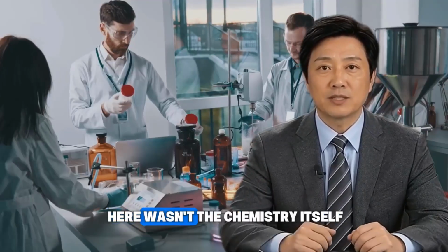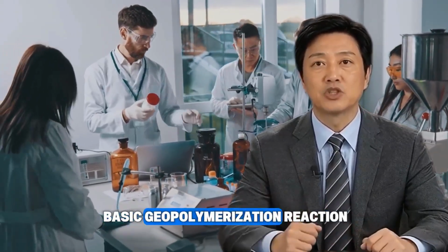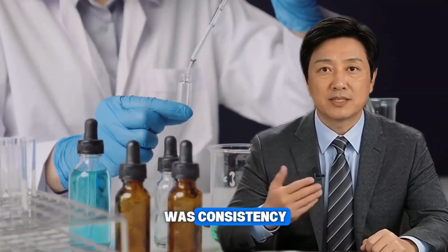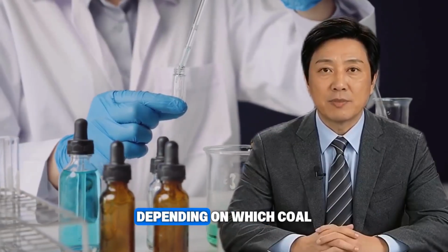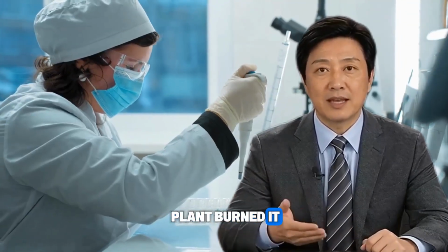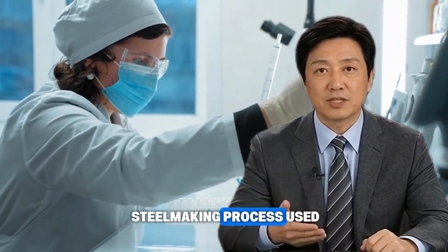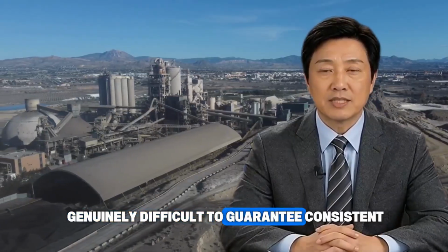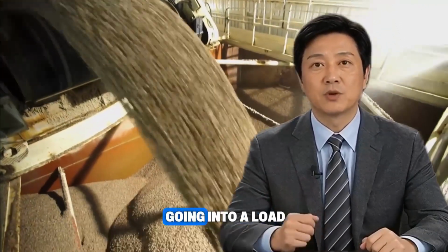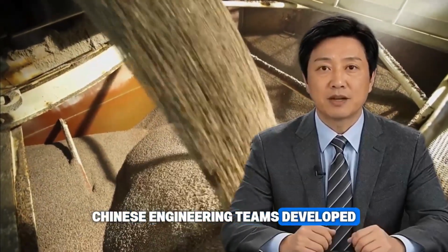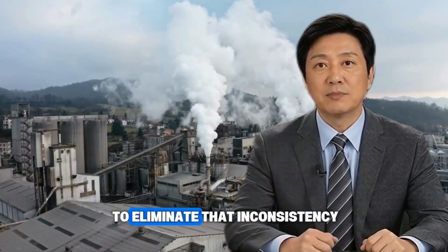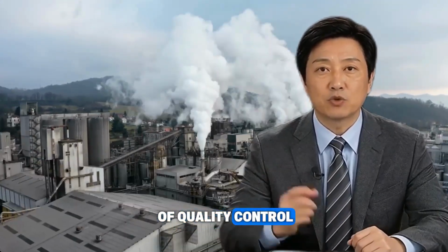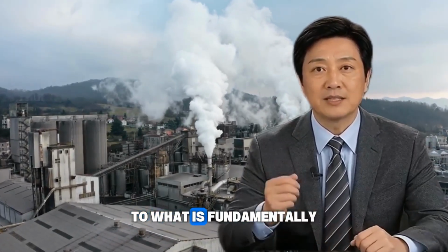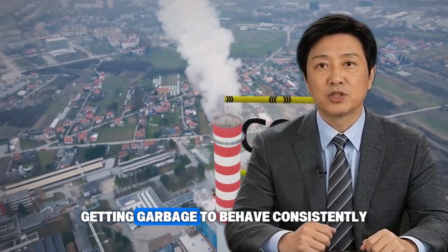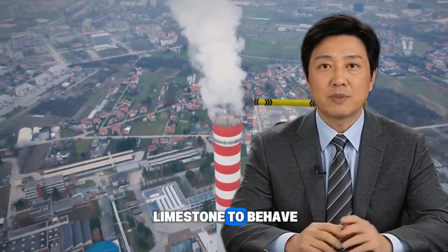The real engineering challenge here wasn't the chemistry itself. Researchers have understood the basic geopolymerization reaction for decades. The challenge was consistency. Fly ash composition varies substantially depending on which coal seam it originated from and how the power plant burned it, and slag composition shifts depending on the specific steelmaking process used. That variability made it genuinely difficult to guarantee consistent strength and curing behavior from one batch to the next, which is a non-negotiable requirement if this material is going into a load-bearing bridge support. Chinese engineering teams developed standardized testing and blending protocols specifically to eliminate that inconsistency, essentially applying the kind of quality control rigor a pharmaceutical company uses on its raw ingredients to what is, fundamentally, industrial waste. Getting garbage to behave consistently turned out to be harder than getting fresh limestone to behave consistently, but they solved it anyway.